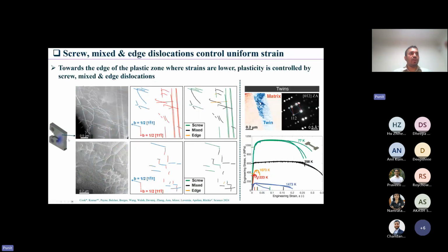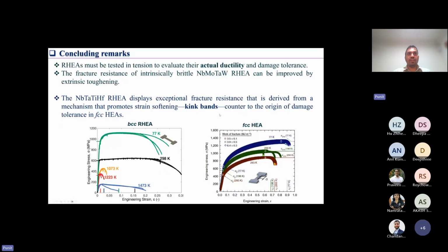So we looked away from the crack tip also to understand what is happening with the deformation mechanism. And in this region, we see the presence of both screw, mixed, and edge dislocations. This is a bit interesting for the high entropy alloy community, because people say that lattice distortion in high entropy alloys slows down the speed of edge dislocations, and we do see some edge dislocations in the material, which suggests that the velocity of edge dislocations has really slowed down. We also saw twinning happening at all different temperatures, so that was also really interesting.